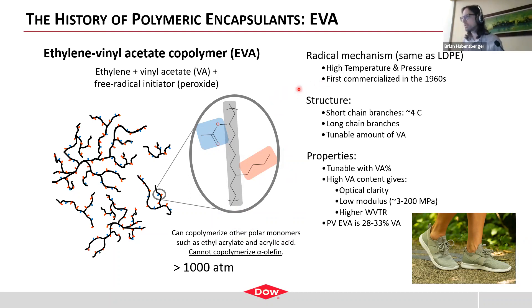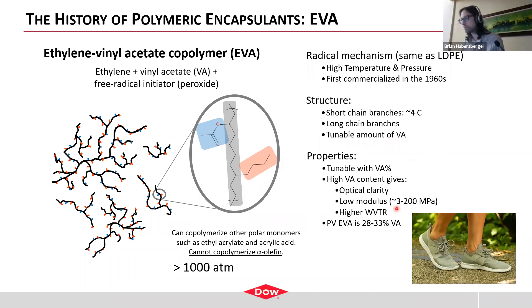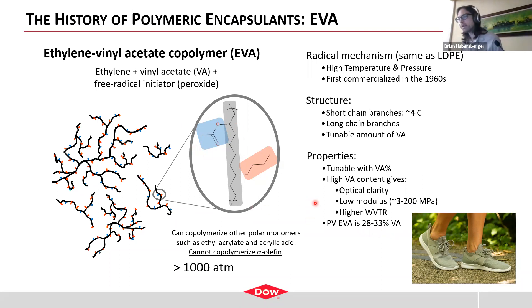The addition of vinyl acetate allows you to tune the properties. With LDPE, all LDPEs have roughly the same crystallinity because there's little control of the polymerization. But with the addition of vinyl acetate, we can control the crystallinity and get a much broader modulus range. With low crystallinity, we can get optical clarity. The VA range used in PV is about 28 to 33 weight percent. However, along with the polar functionality of the vinyl acetate, we get a higher relative water permeation compared to something like LDPE.